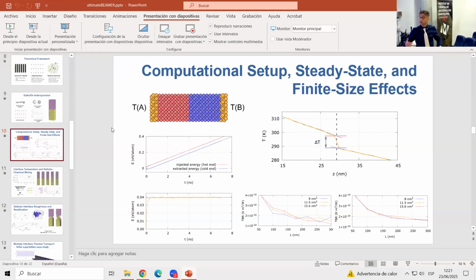I would expect that if you take a couple of materials exhibiting a different acoustic impedance, for example, according to the acoustic mismatch model, you would observe in principle a higher, a more enhanced thermal boundary resistance. And this is just pretty general. I think this could work in a very general way of speaking.